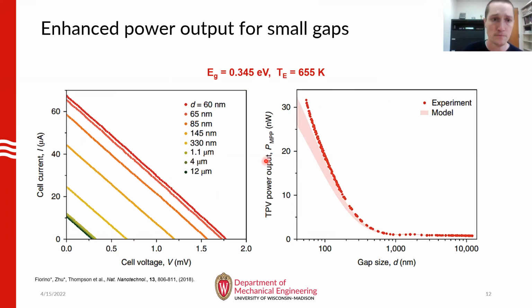But basically, yeah, this indicates that the smaller the gap, the higher the power output you can get. So on the right, from these IV sweeps, you can get the maximum power point of the PV cell. And that's plotted on the right as a function of the gap size. So as you can see, as we reduce the gap size from around 10 microns to 60 nanometers, we see a 40-fold enhancement in the electrical power output compared to the far field power output. And this result also agrees quite well with the FED framework, which we use in combination with a detailed balance of the PV cell. Okay.